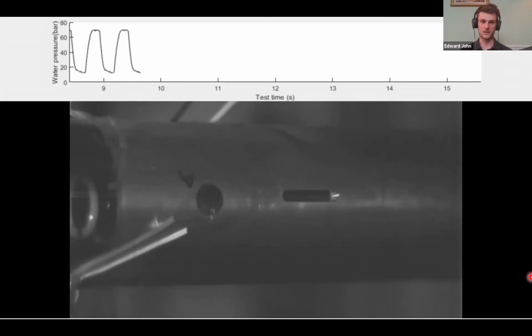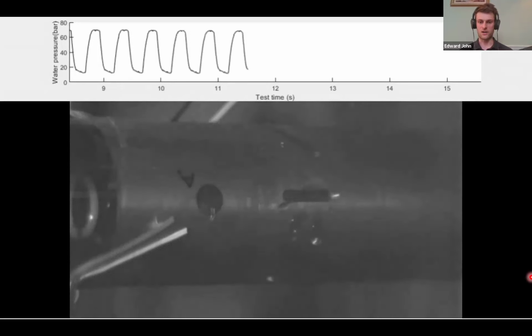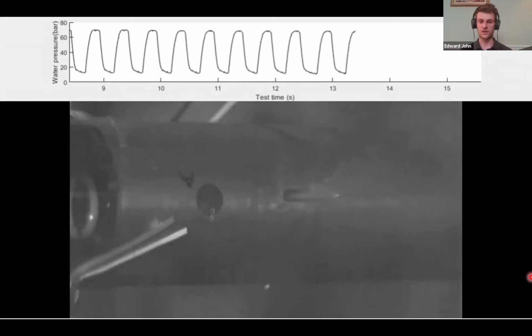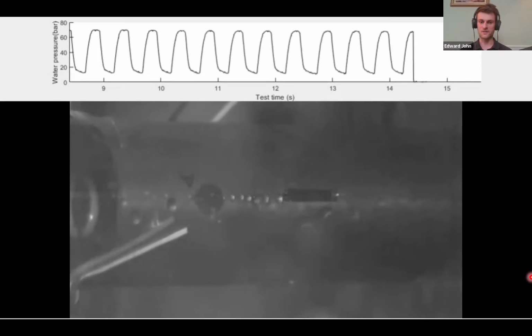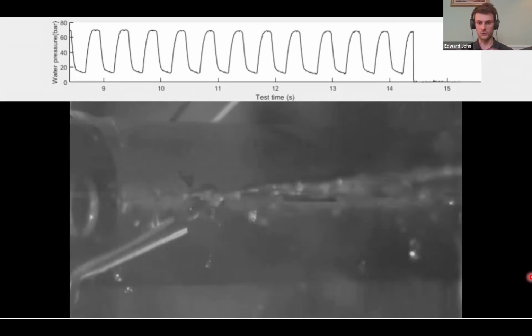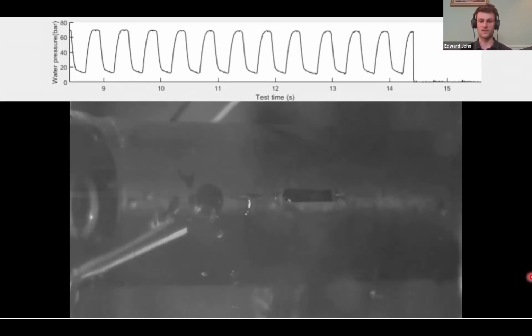The pressure is just cycling twice a second in these tests. And then suddenly we have a crack form at the base of the pit. This crack has taken up the whole length of this pit. And interestingly, it's only leaking during the higher pressure part of the cycle, and the pressure is always positive during these tests. And then after 10 cycles, the crack was able to propagate beyond the pit, and we basically have a burst.